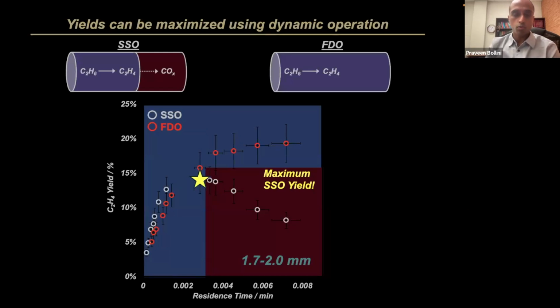What we're able to do with the switching is exceed this yield maximum. Your yield still has a trade-off, but the residence times at which you observe the maximum are extended quite a bit. So what this means is that the maximum yield that you can obtain for ethane to ethylene to COx or CO2 is increased significantly when you operate under dynamic conditions compared to steady state conditions.